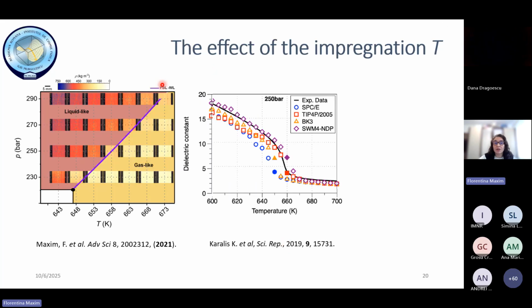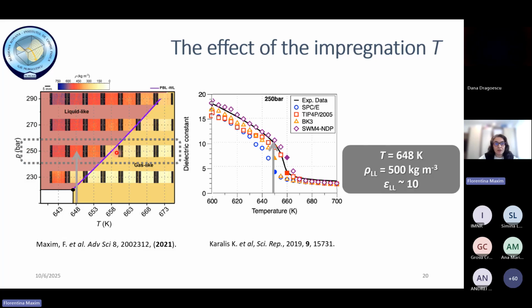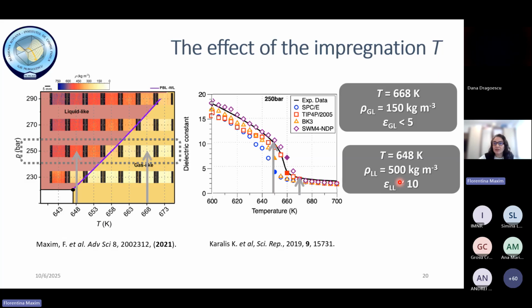For the materials development, we again based our synthesis preparation of the material on neutron imaging measurements, because we determined the temperature of impregnation based on these measurements. So we were sure that at 250 bar, the isobaric conditions, we did the impregnation. At the temperature 648 Kelvin, the water is in the liquid-like state with this dielectric constant, but at 668 Kelvin, water is in the gas-like state with this dielectric constant. Of course, this property variation between liquid-like and gas-like determines how the reactions are undergoing.